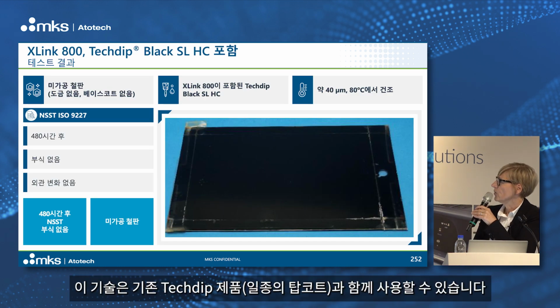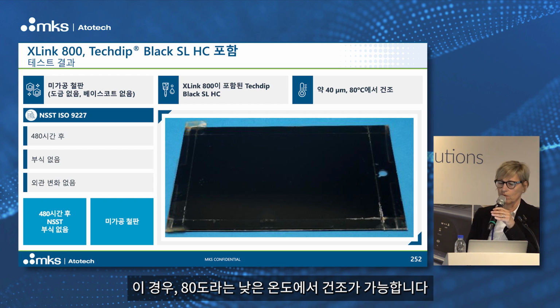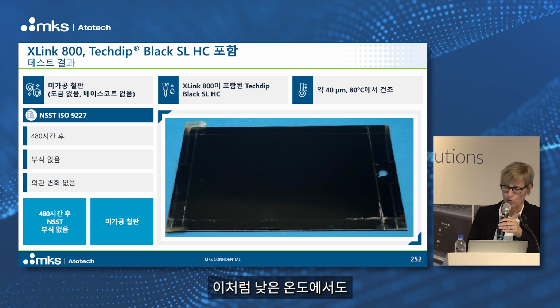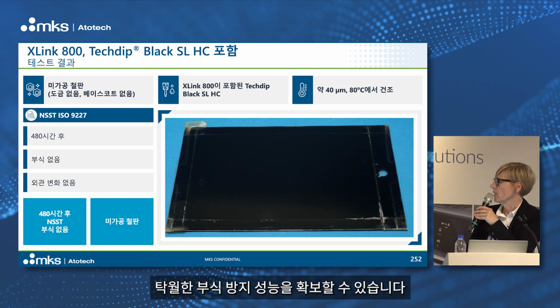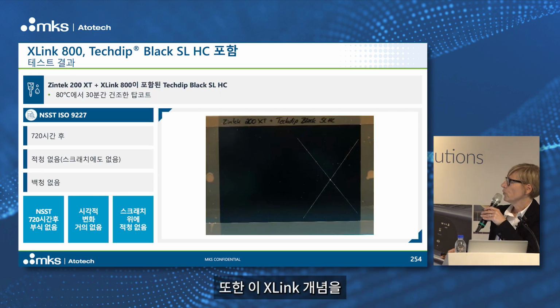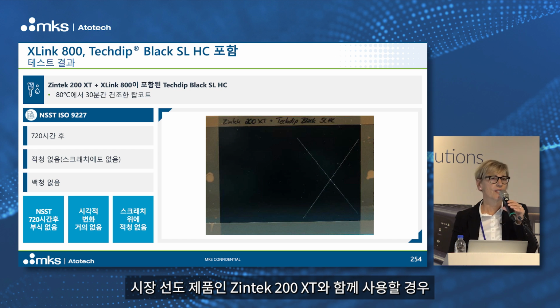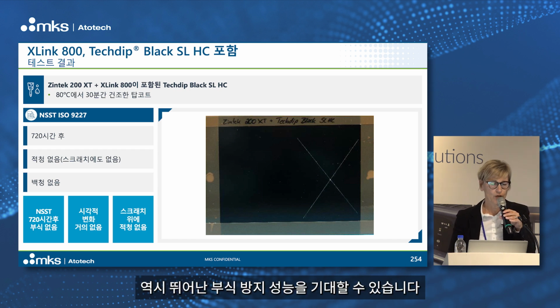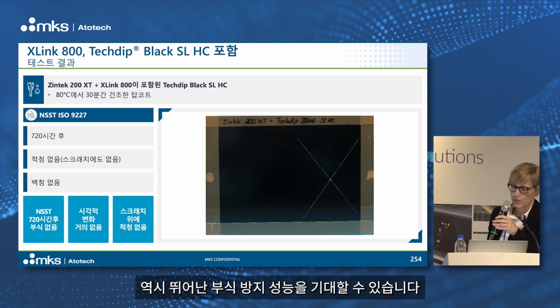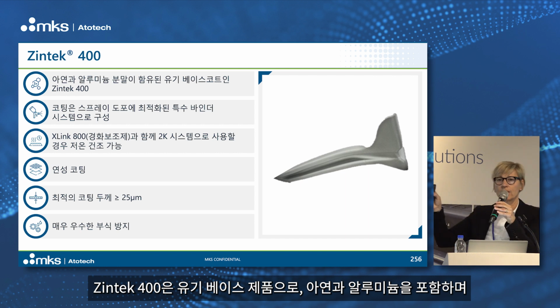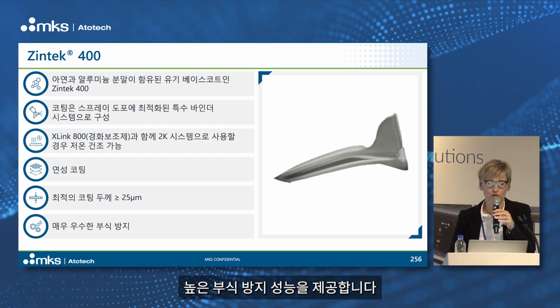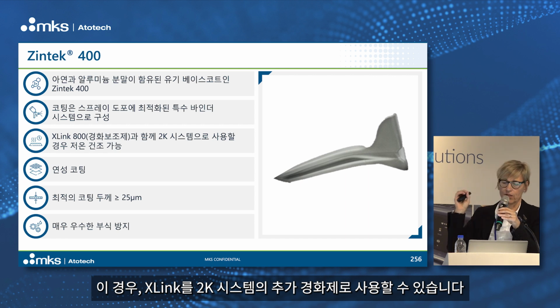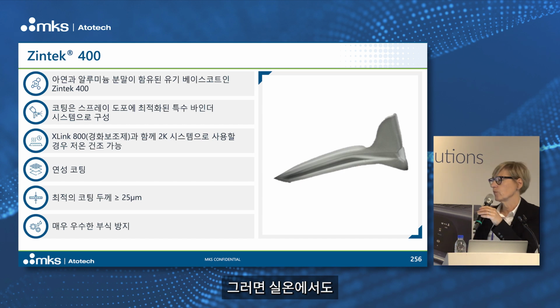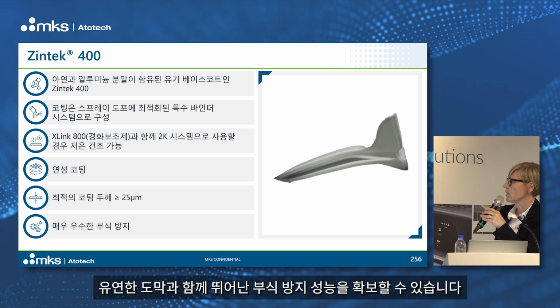On one hand, you can use that with a normal tech dip, which is a kind of our top coats, and here you will see then reduced temperatures, only dried at 80 degrees. So really also with these low temperatures, you can get excellent corrosion performance. And if you are using this X-Link concept also with our usual Zintek 200 XT market-leading product, then of course you can also expect excellent corrosion performance. And even with our Zintek 400, which is organic base and zinc plus aluminium, so also high-performance corrosion protection, you can use this X-Link as additional cross-linker in a 2K system, and then even at ambient temperature, you can get excellent corrosion performance with a ductile coating.